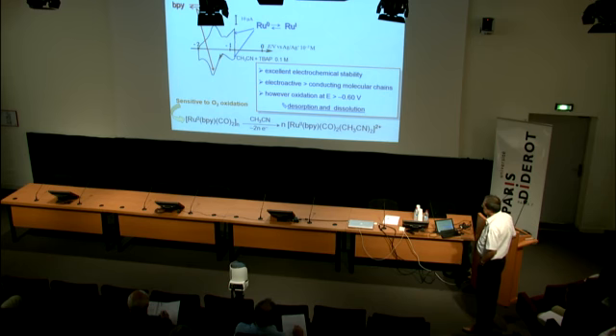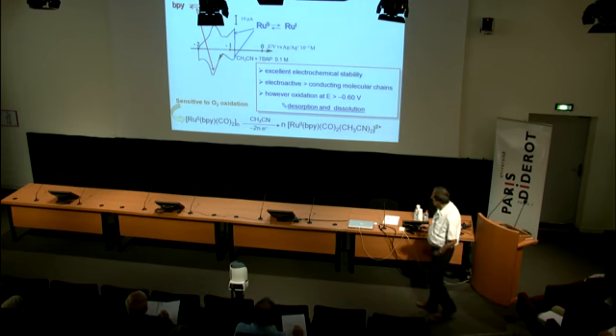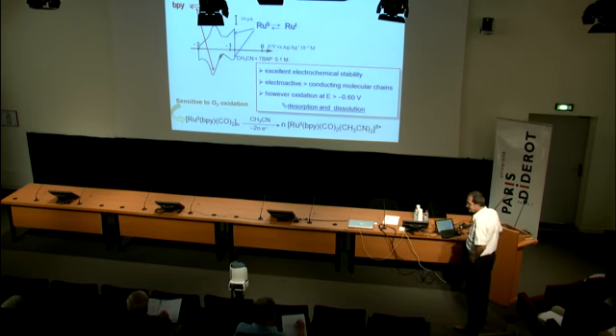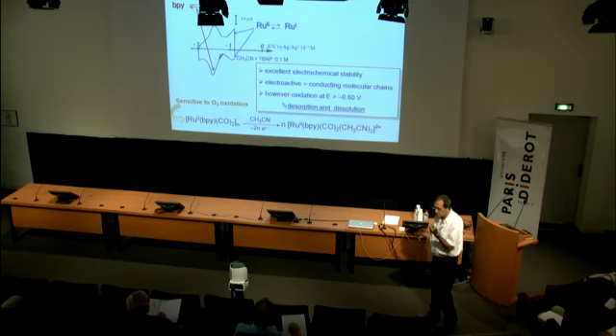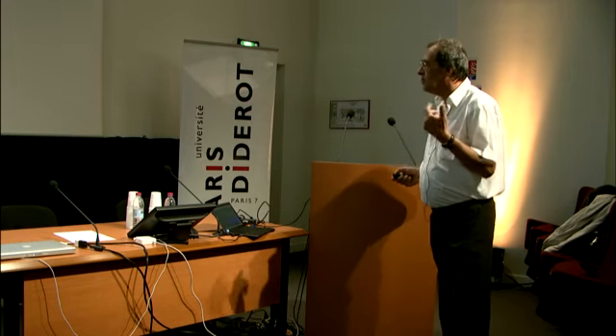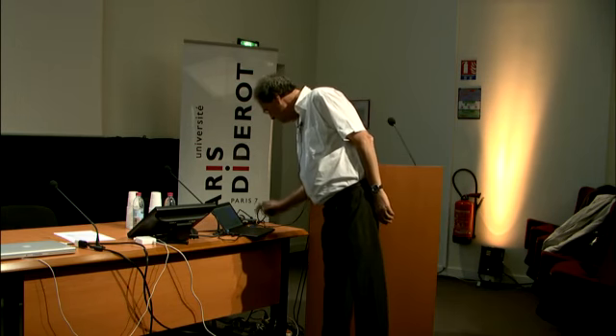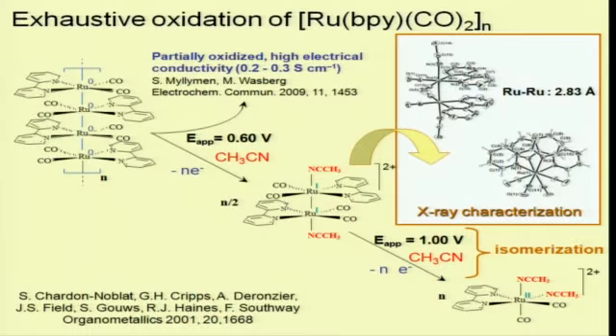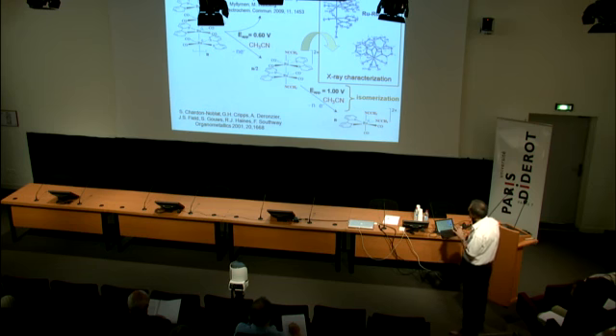And we have demonstrated, for instance, that the complex, the polymer, can be oxidized following a two-electron process. If you do that in acetonitrile, in fact, you come back to the starting material, except that the initial chloroligand is replaced by two acetonitriles. Well, we have studied in great detail the oxidation of the film, and we have demonstrated that we can see two different steps.